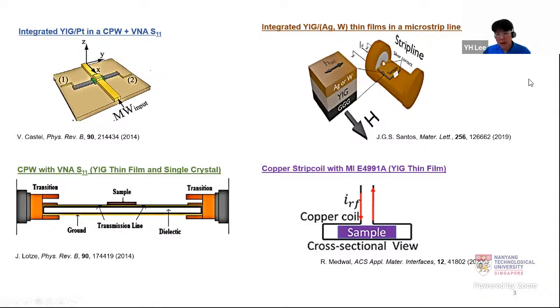gigahertz. Top right by J.G.S. Santos, in this case, they investigated the effects of different capping layers, namely the silver and the silver and tungsten on the YIG thin film, and the effect it has on the Gilbert damping parameters. Somewhere near us in the NTU NIE, led by Dr. Rohit, they investigated the magnetic field dependence electrical impedance using a copper strip coil.